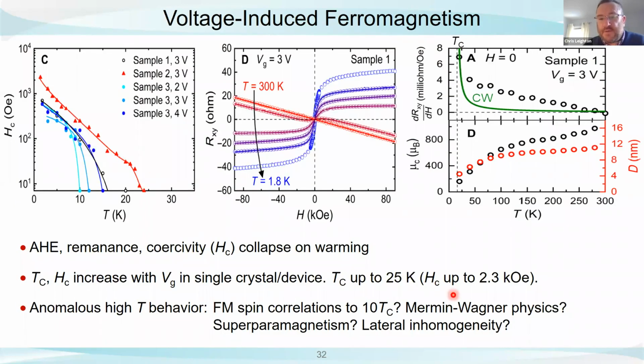If we're in the 2-dimensional limit and we have a soft ferromagnet, we only have hundreds or maybe thousands of Gauss of coercivity. It is possible that what's happening here is the system wants to order at very high temperatures. It has ferromagnetic correlations at very high temperatures, but it just can't order until low temperatures. That's one possibility. The other is the solid lines that I show in this plot. They are fits to the Langevin equation, so they are fits to superparamagnetism, okay? And they work quite nicely. They don't work perfectly because it turns out that the size of the cluster is not constant as a function of temperature, which I see as a bit of a limitation.